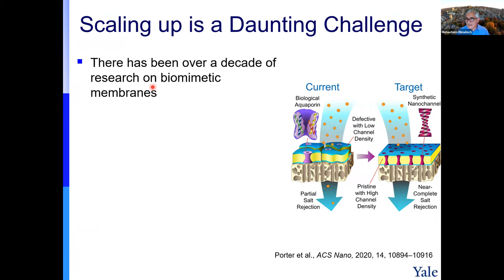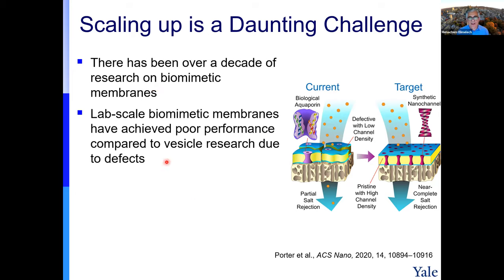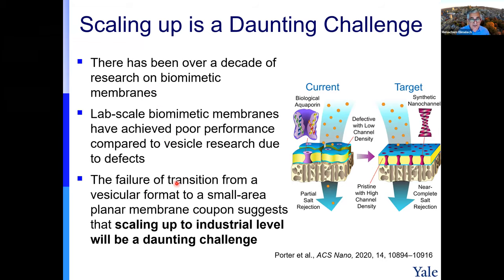So there has been research on biomimetic membranes for desalination for over one decade. And although we can show their good performance in vesicle format, and this is the way we measure them, any attempt to have a planar membrane, even a size of 1 cm², failed. You cannot get high rejection because you cannot create such a thing. It's a lot of defects. So my conclusion, if we fail to move from vesicle to a very, very small area, 1 cm²,